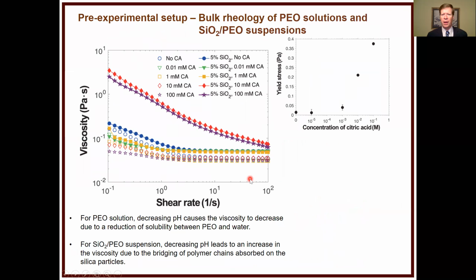And so just to talk a little bit about the rheology and changing pH and how that has an effect on the system, what we're going to do now is just put polymer and water. These are all the open symbols. And as I decrease pH, what happens is you have a decrease in the rheology, and that's because it becomes a theta solvent or a poor solvent for the polymer, and it balls up on itself and lowers the viscosity. Now, as you can see, we also have shear thinning until we get out to roughly between 1 and 10 inverse seconds.